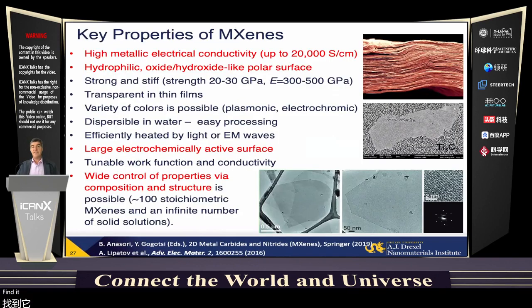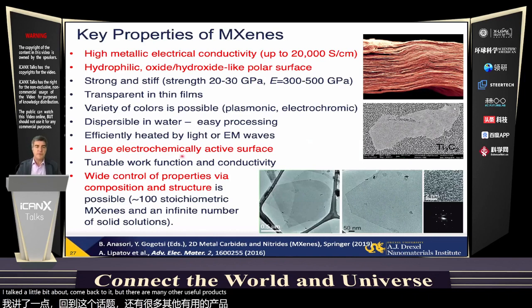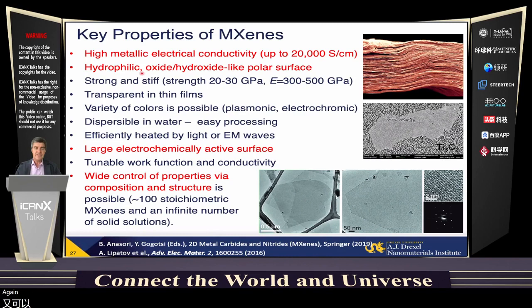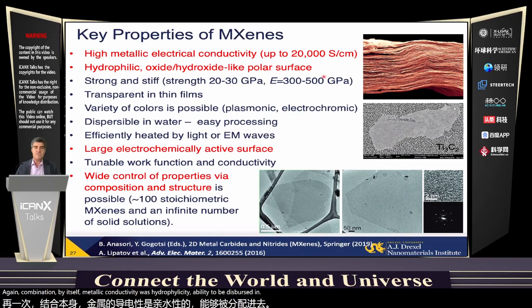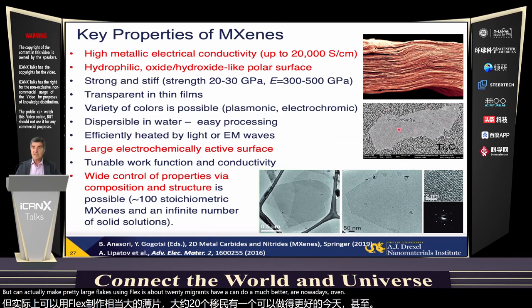Now, I talked a little bit about conductivity, but there are many other useful properties of these materials. Again, the combination by itself of metallic conductivity with hydrophilicity, the ability to be dispersed in water or polar solvents, provides a very unique combination of properties. Moreover, we can actually make pretty large flakes. This flake is about 20 microns. We can do much better nowadays even, and it doesn't break.